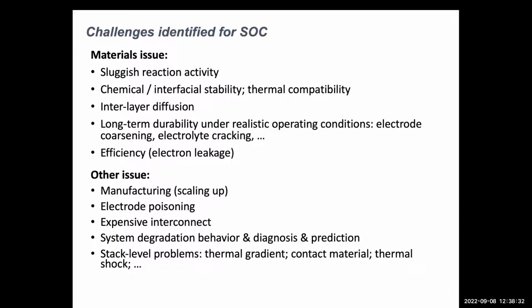And another is interlayer diffusion. This is element diffusion, because each layer contains different elements. At a high temperature, the elements can diffuse through to the other layer, which can cause other kinds of issues. Another important topic is long-term durability under realistic operating conditions. Realistic conditions mean high temperature, high steam, and high current density, which can challenge the materials' stability. Such as in long-term operation, we can see the coarsening of nickel particles. We can see some cracking in the electrolyte layer, as identified by people.